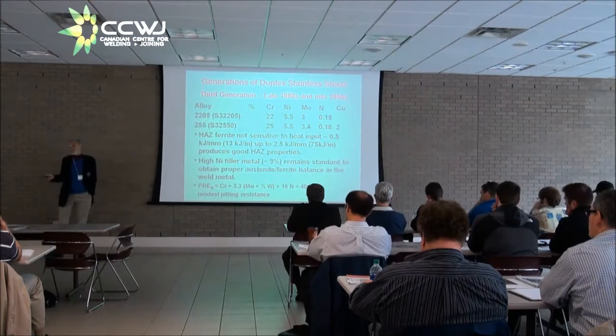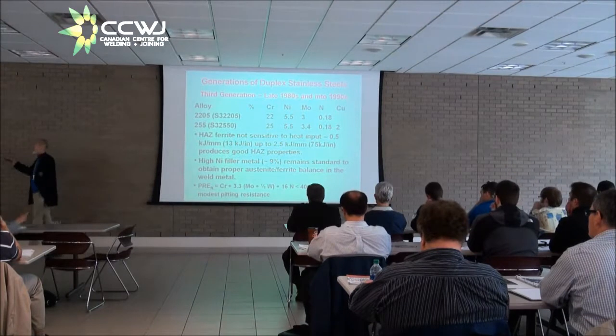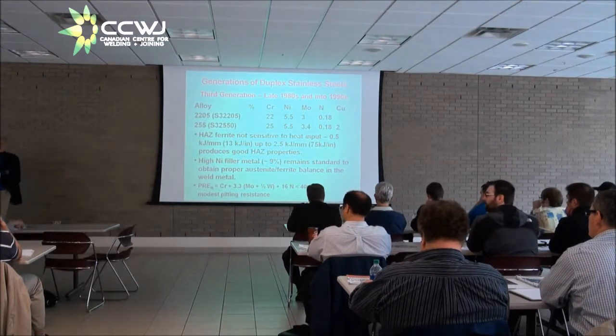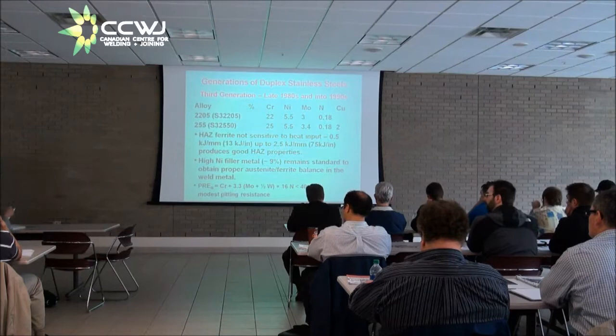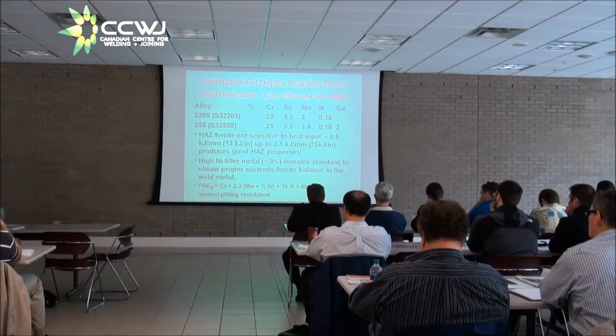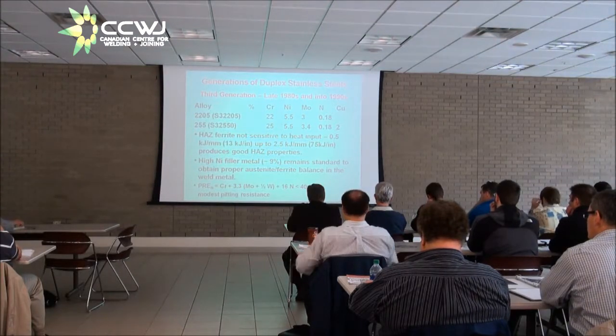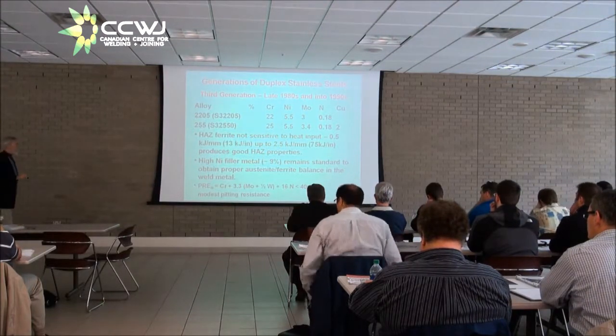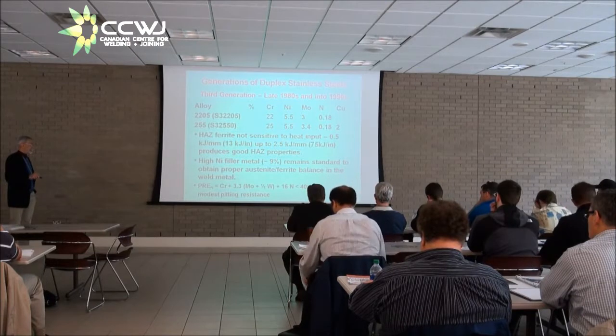And now we start looking at pitting resistance, but it's only after we got to the third generation of duplex stainless steels that we thought at all about pitting resistance. As I said earlier, chloride stress corrosion cracking was the main reason for duplex. And now we can look at this pitting resistance index, which includes nitrogen.